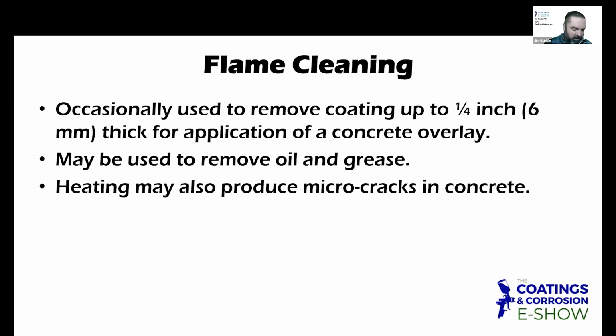Flame cleaning is done where you're basically using flame to remove coatings and things like that. But it can also be used to remove oil and grease. Now, when you're dealing with flame, you run a risk of having explosive pop-outs, because you have these air voids underneath the surface of concrete. As that heats up, it could pop out and blow concrete out on you. But also, when you're using heat, it can produce micro-cracking in concrete, which can become problematic. Sometimes it might not be, but there is a higher potential of problems as you have micro-cracking in the concrete with a coating system over top of it.